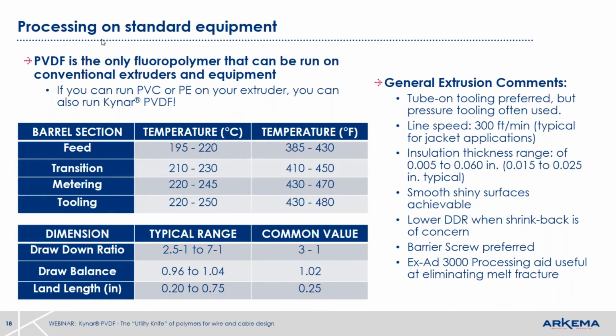Processing. A key element to using PVDF is that it is the only fluoropolymer that can be run on conventional extruders or molding equipment. If you can run PVC or polyethylene on your extruder, then you can run PVDF. It's just as simple as that. So anyone that is not in the fluoropolymer business and wants to get into it can by using PVDF. So you can see the extrusion temperatures that we recommend, and the drawdown ratio and draw balance, land length that we typically recommend.